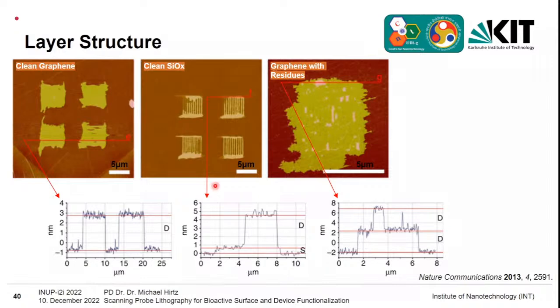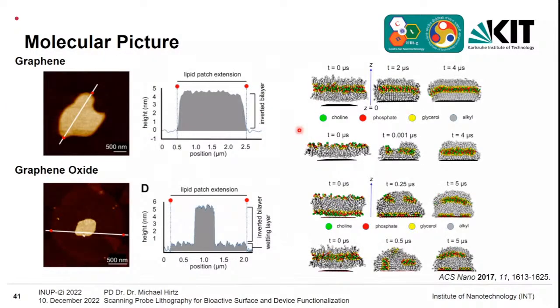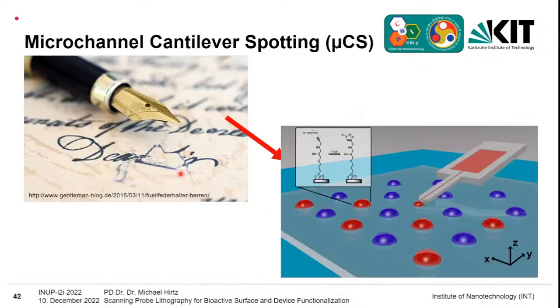If you look at AFM, we can see again these layer structures that I talked about. This is all done in air, and you can see that on a clean graphene that's more hydrophobic, you have only one layer. And on the silicon oxide, you have this wetting layer, the single layer, and then the double layers on top. And this is also confirmed in a molecular picture by molecular dynamics. For time reasons, I don't want to go too much into this, but you can see that we have this control over the configuration by having either more hydrophobic or more hydrophilic surfaces. This is what I wanted to say.